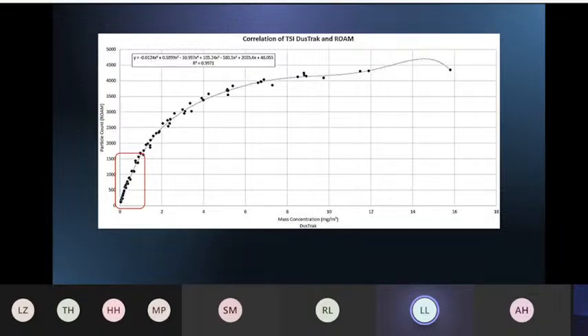So what you see here is what we tried as a sort of laboratory test. We call it the smoke diffusion test, and my associate actually tried to place a benchtop aerosol monitor, the TSI DustTrak, together with ROAM, inside the box where there's initially some amount of smoke, and then we let smoke diffuse over time. And as you can see, just going through the small portion of the curve that is highlighted in red in a rectangular box over there, there's actually a high correlation coefficient of 0.9971. So our unit measures almost exactly like the TSI DustTrak.